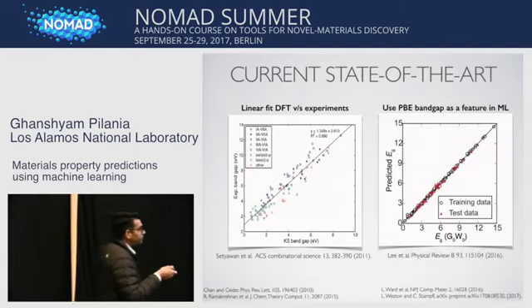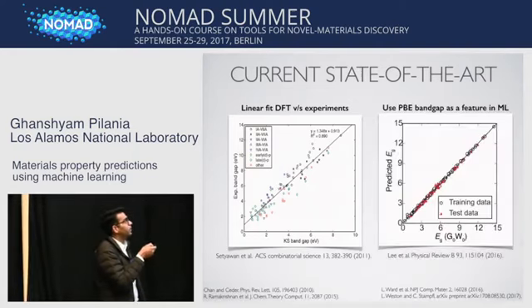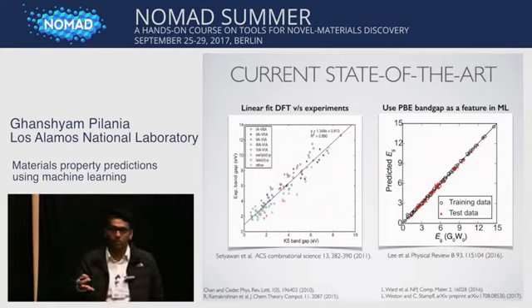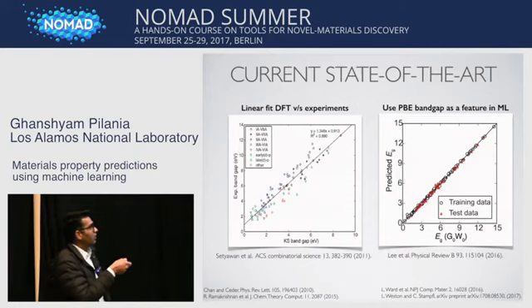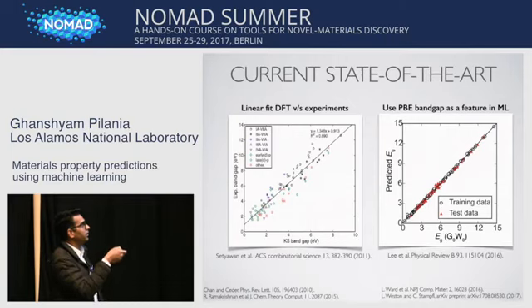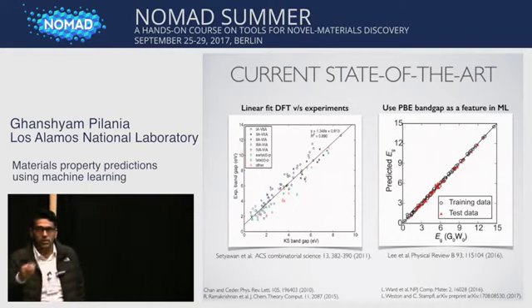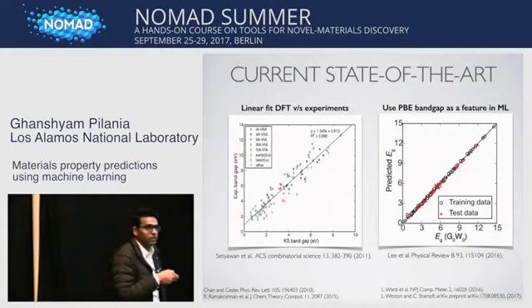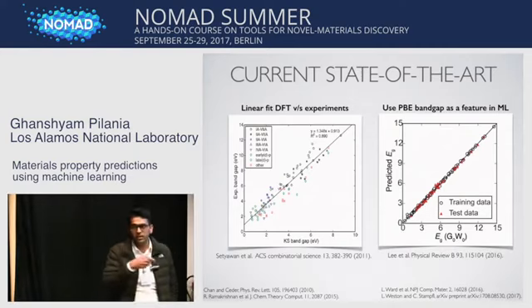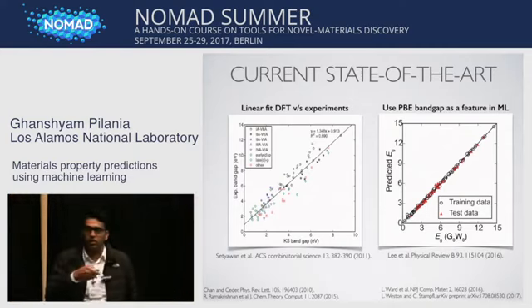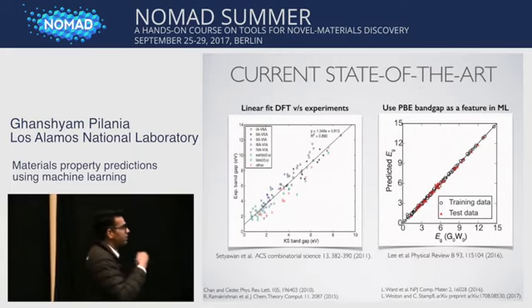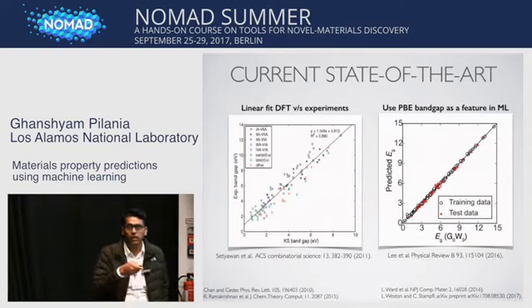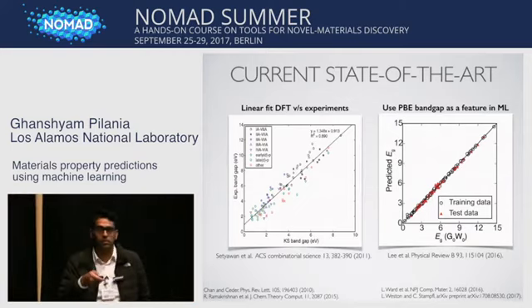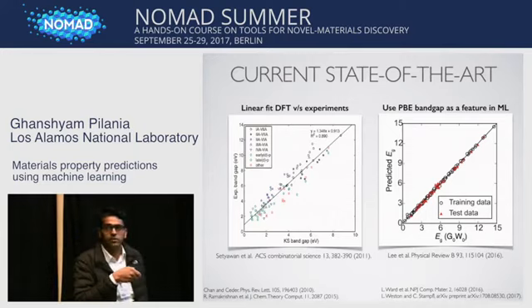On the other extreme, one can use PBE band gaps as a feature of the machine learning itself. So recently, Lee and co-workers showed that GW band gaps can be predicted very accurately if you use PBE band gaps in addition to the atomic features in the machine learning model. In this particular case, they use support vector regression. And you see that predictions are really good. But the deficiency is, if you are going to use such a model for much larger chemical space, then for every prediction you are going to make, you need a DFT calculation, because you are using PBE band gap in the machine learning model as a feature.